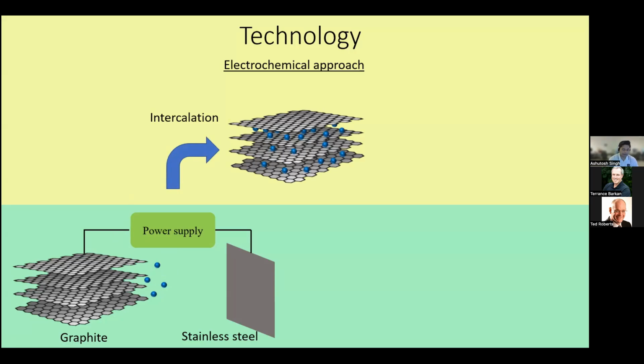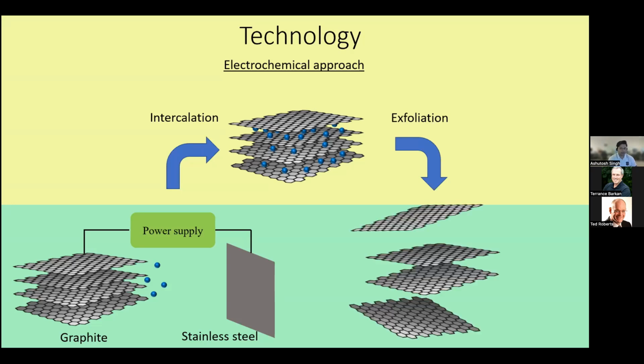As it completes, water electrolysis takes place, because the water molecules are not interacting by themselves with it. These water molecules convert into oxygen. That creates a pressure between the layers, and that process, which we usually call exfoliation, pulls the layers apart. This is a schematic to understand how this approach works. What we found is that by doing this, we were able to save 70% more energy. It was 70% more energy efficient compared to conventional chemical methods.